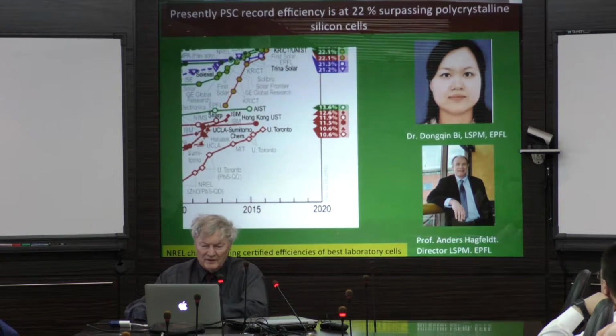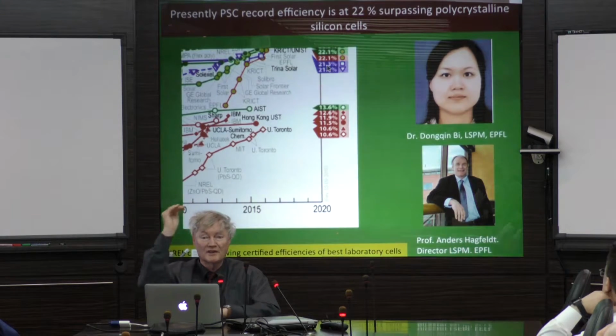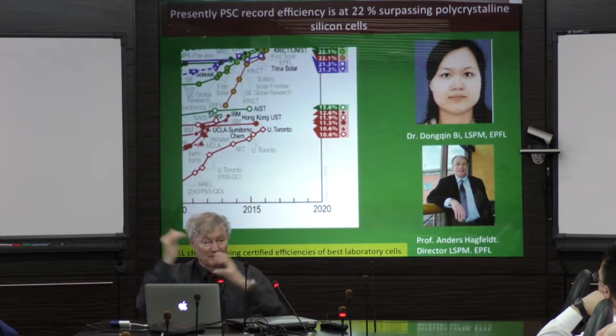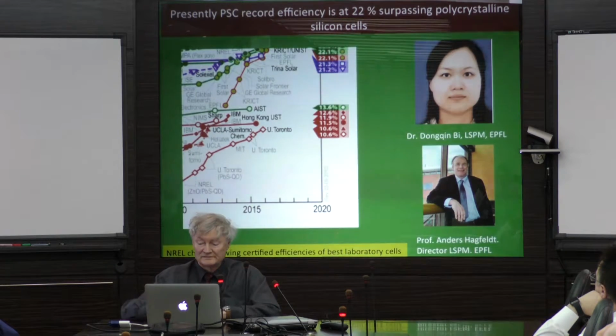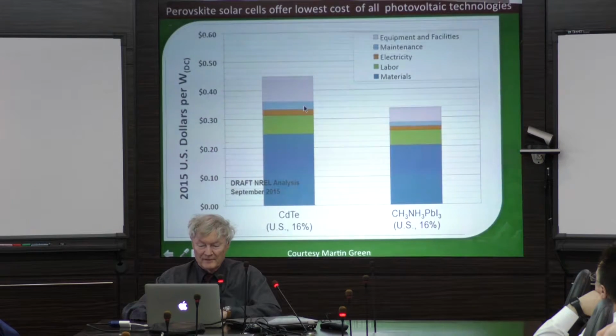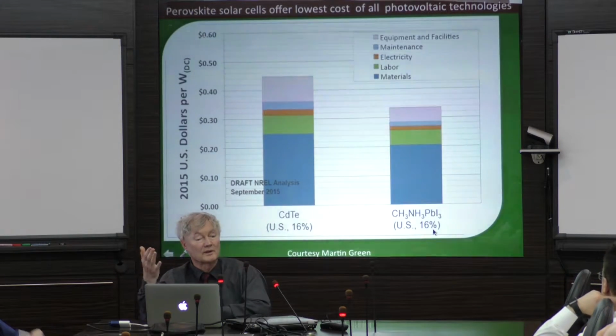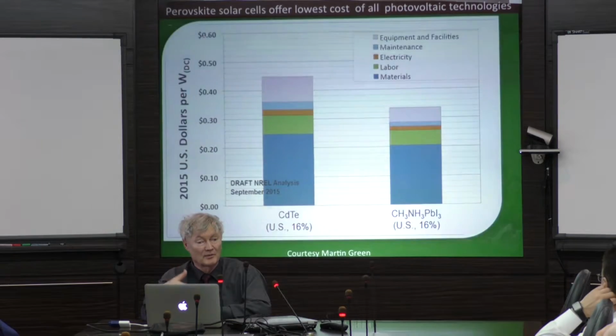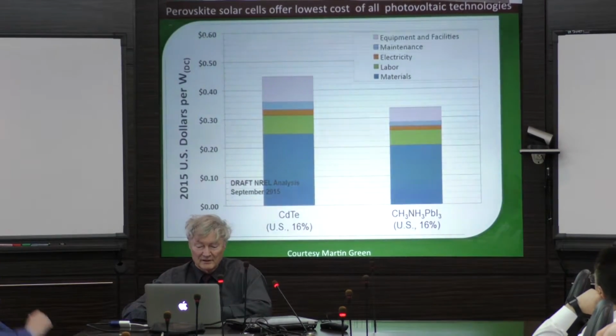And so, as I said, we have seen this technology go up in efficiency, and now we are up at 22% conversion efficiency. And you see, that's the red entry you see here, 22%, and the blue ones are for silicon. So for the first time, we see the perovskite beating silicon photovoltaics. And here comes some cost analysis. We have panels rated 16%. Well, that's far below what we have already reached with the perovskite solar cells. But still, they use this as a comparison, a 16% panel, and the cheapest competitor is cadmium telluride.